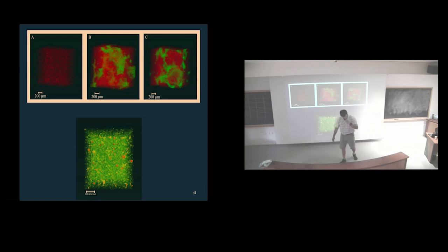Another excellent question. Many people have proposed that blooming is if you get cracks and you get some liquid oil, it travels up to the surface and creates a surface of crystals. Imagine if you had a smooth surface and now you have crystals standing up like that, light impinges and it scatters light, and that's your bloom chocolate, usually an uncontrolled crystallization to form 6. You could say that some people would not be very happy to have cracks because that could induce bloom formation.